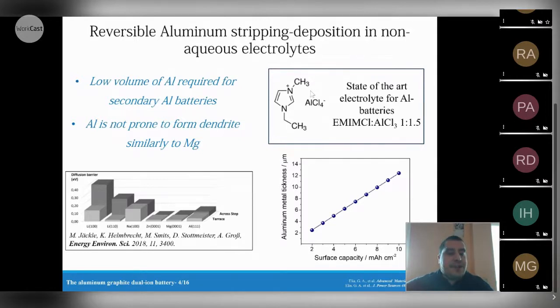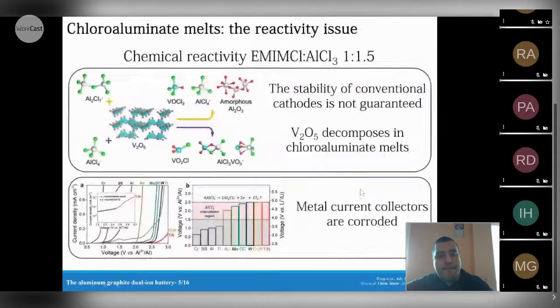And one of the main advantages is that in this system, aluminum is not prone to form dendrite, similar to magnesium. And moreover, thanks to the elevated energy density, we need only a limited thickness or a limited volume of aluminum metal to obtain a reasonable surface capacity that is needed for the battery realization. Clearly, there are also several disadvantages in the use of this chloroaluminate melt. Most of it is related to the elevated reactivity of chloroaluminate melts, and here a nice example is a manuscript recently published by Professor Guo, where he investigates the chemical stability of vanadium oxide, one of the most widely used oxide materials for multivalent system, in aluminum chloroaluminate melt.